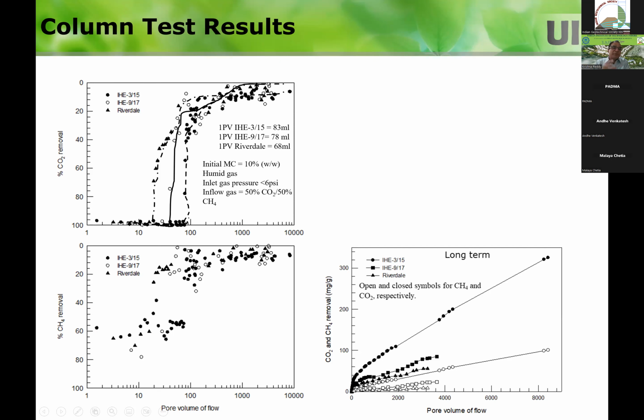This is the column experiment. So you're putting from the bottom, you're measuring on the top. Nothing comes on the top until you reach certain pore volumes. A significant number of pore volumes are needed. It's like 100 pore volumes are needed to see something coming out. So this is all total sequestration. And then it comes out, and then you see eventually inlet and outlet become the same. So based on that, you can calculate how much is the CO2 removal.